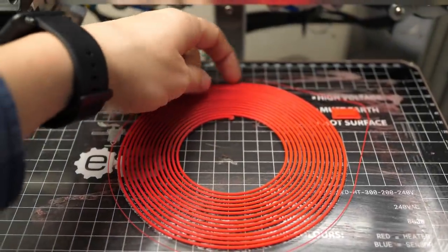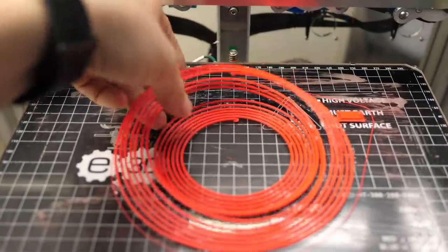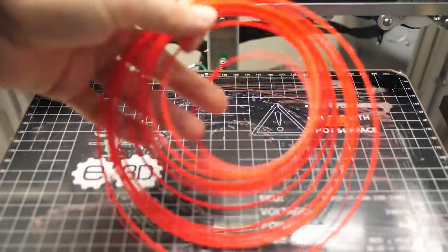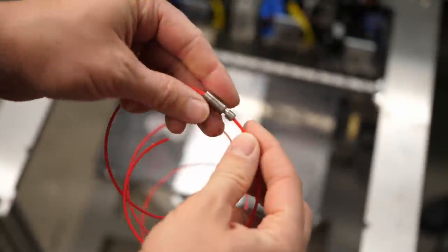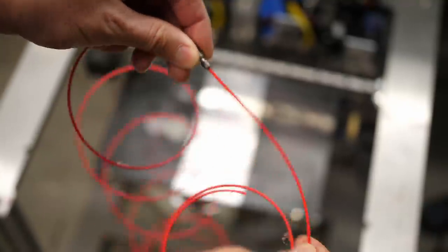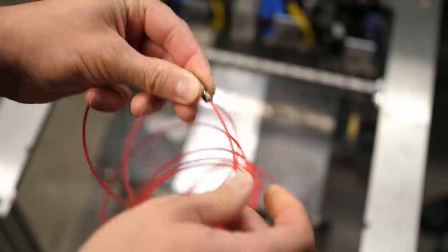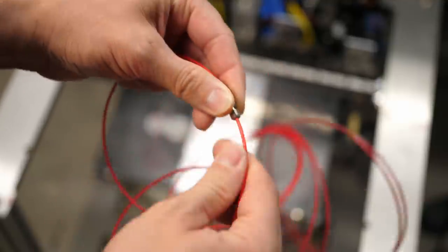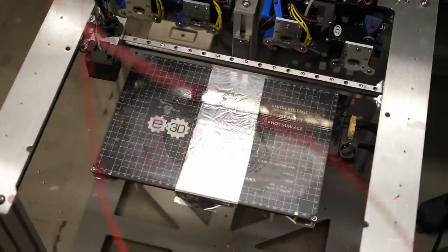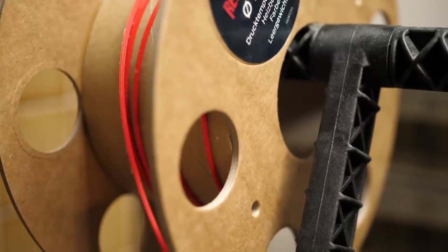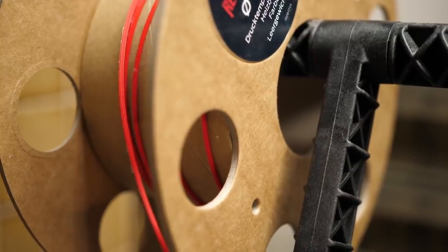Manufacturing the dual material filament still overall worked quite well and I printed spiral after spiral and checked at least the maximum dimension that was sometimes a bit too high due to the material lifting by just pulling it through a spare heat break. This way, I could prevent jams during printing. Dimensions themselves, even though around the circumference not always perfect, were quite consistent over the length. I put the coils on empty spools and printed with them on my Prusa MK3.